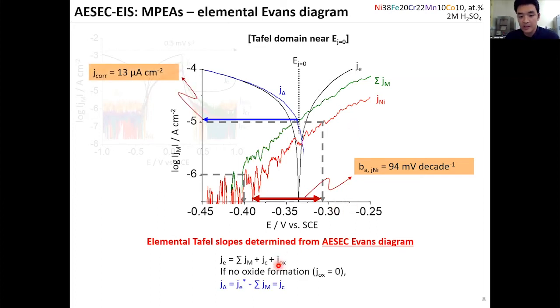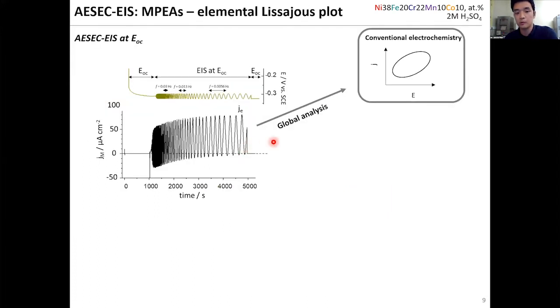And when we do the mass balance calculation for this case, assuming that there's no oxide formation at this condition, this J delta could mean the contribution of cathodic current. So in this case, we can construct a mixed potential theory for an elementally resolved case, so that we can extract the corrosion current density for this system. So it also can be used for the long-term corrosion of these alloys.